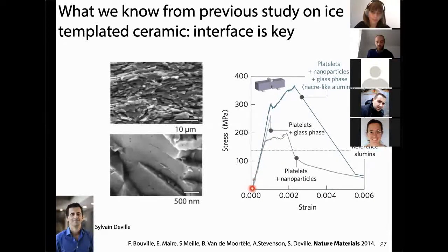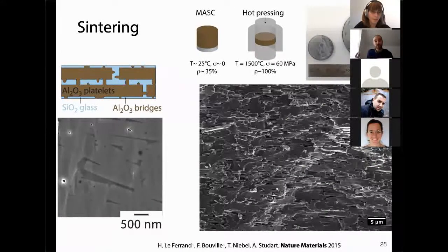and you also put these nanobridges, what you end up with, when you test it in crack propagation, is again a fairly high crack initiation, but also a very stable, slow crack propagation, which is quite unusual for something that looks like a very normal bulk ceramic. So we revisited this material with this brand new process, because we had better alignment and could better control the structure and the density of these composites.